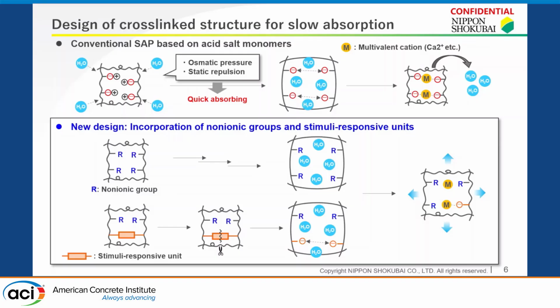Furthermore, the combination of nonionic groups and stimuli-responsive units enables the SAP to increase its absorbing rate as these responsive units gradually cleave in concrete. This innovative approach is expected to enhance the internal curing effect by supplying water to the cement as relative humidity decreases.